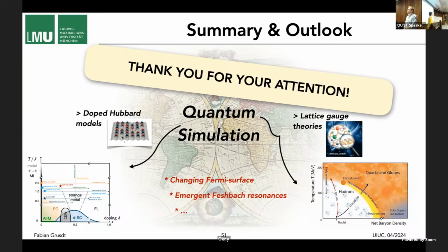Here we do see some differences, which we find interesting: the spin gap is not always the same as the pairing gap, and especially these string patterns. For example, I showed binding energies that exceed the superexchange energy, and this is only possible because of the strings that form. That's not true for the spin gap. The spin gap always scales roughly as J. In these systems, it doesn't disappear. When I showed you the binding energy, it remains positive all the time. That's one of these quantitative details.